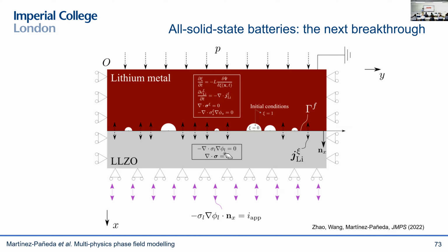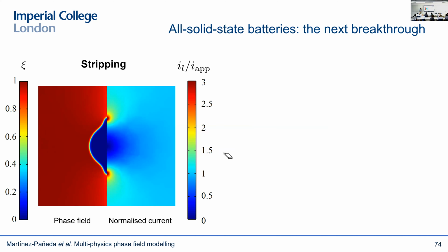So you can see here the boundary value problem and equations. We solve a transport problem, a phase field problem for the evolution of the voids, a mechanical problem with viscoplasticity, and also an electrical problem. We want to see those hotspots that we discussed before. So these are some representative results. This is stripping. On the left, you're seeing the lithium metal; I'm plotting the phase field on the left and the current on the right. You can see that the void does what we saw in the experiment, so it expands, and you see those current hotspots there. So naturally, the model is able to capture the localized current near the edges of the voids.